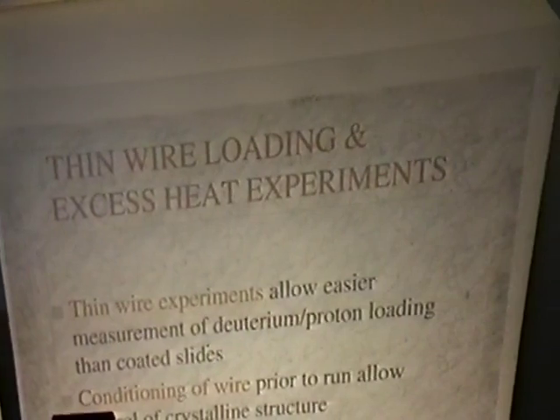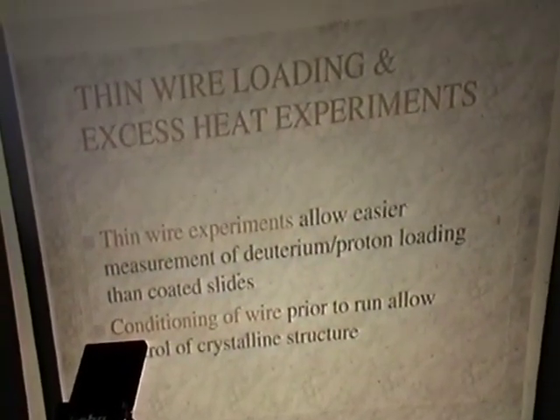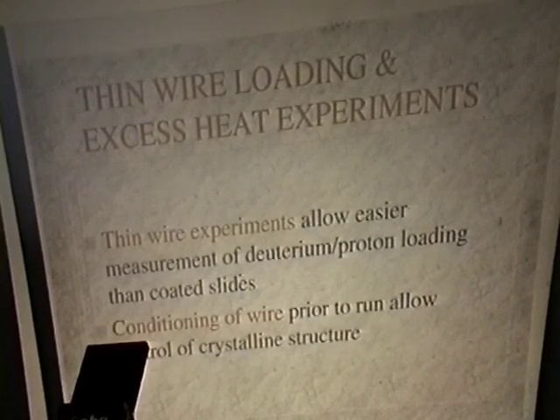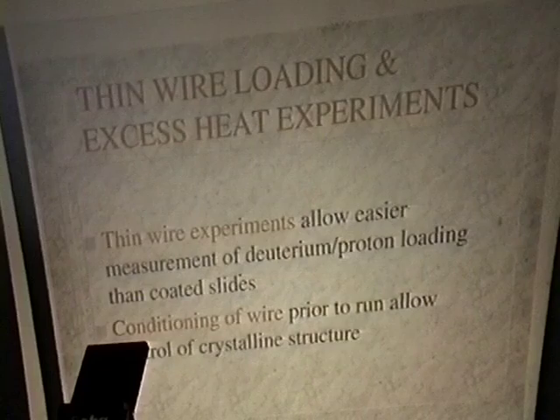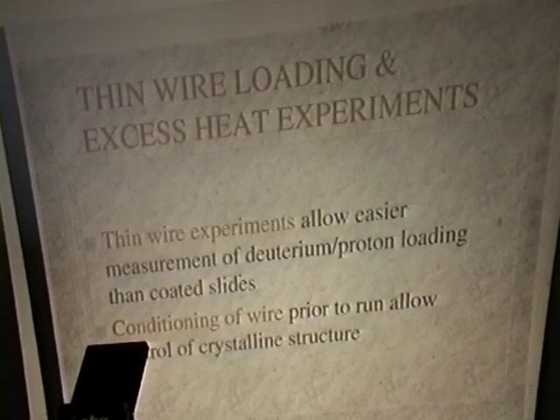Well, that ends the brief review of the reaction products, and I move to the question of thin films. What we did recently was an experiment inspired by the work done at Frascati with thin wires, as an attempt to better understand thin films. Thin wires have many characteristics like thin films, one of which is that you can get high loadings with minimal problems of micro cracking due to stresses, since the stresses can be taken up to some extent. And so the experiment that we did was to try to understand better the relationship between excess heat and the loading.